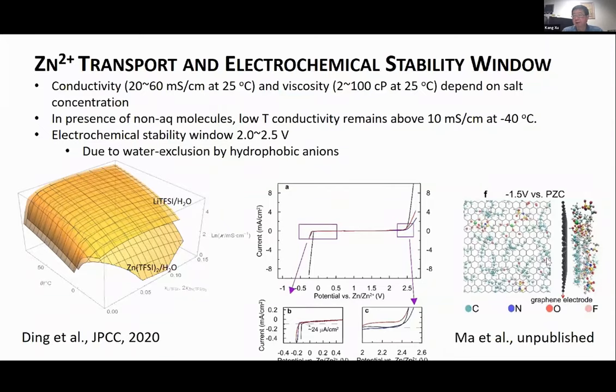And by studying the interfacial structure, or inner chemical structure before the interface forms, we found that the addition of those phosphonium salts acts as a strong hydrophobic structure former, and at the interface, both anode and cathode side, they serve as a key ingredient which expels water from the chemical layer. That helped us to suppress the hydrogen and oxygen evolution reactions and gives us a better electrochemical stability window to work with.